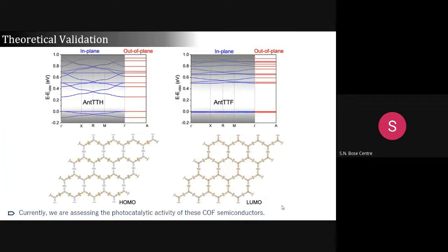Yeah. So from this, it's a little bit clear. Here you can see continuous conjugation through the chain. But if the anthracene is in a non-planar position, then the anthracene unit will have a localized HOMO. With the localized HOMO, there will be no conjugation, so it will act as a trapping center, so you may not get good transporting property. That is why planarity plays a crucial role for this kind of material to give good transport.